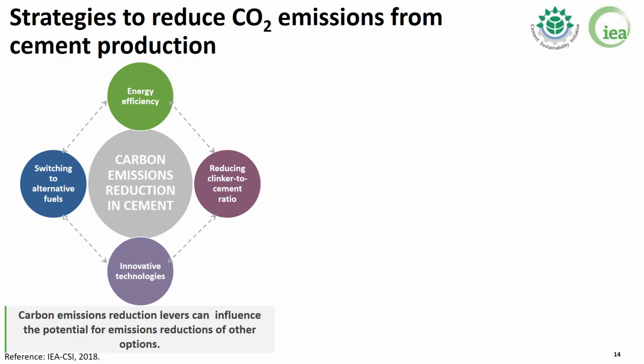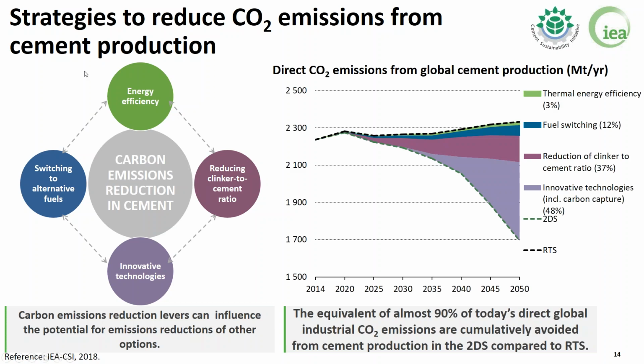For instance, the implementation or a higher uptake of alternative fuels would contribute with an upward effect on the energy footprint of cement production on the cement kiln, because typically this type of fuels have a lower calorific content. So those types of interactions are also explored in the roadmap. To do that, we developed 2 scenarios.